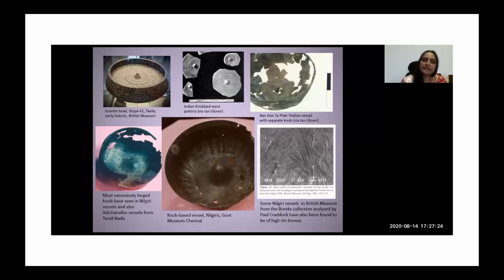But they were aiming at this beta phase composition. But if you see that Nilgiri vessel, it's really fluted, and the knob is very well formed with the rings around and so on. And also, there has been some microstructural analysis done, for example, by Paul Craddock on the Breeks collection, which also shows that it is 23% quenched beta bronze. And there you see this extensive beta phase again, very good formation of this martensitic beta phase. So this exploitation of the beta phase seems to have been particularly well done in some of these examples, which are found in the context of the South Indian megaliths or cairns.